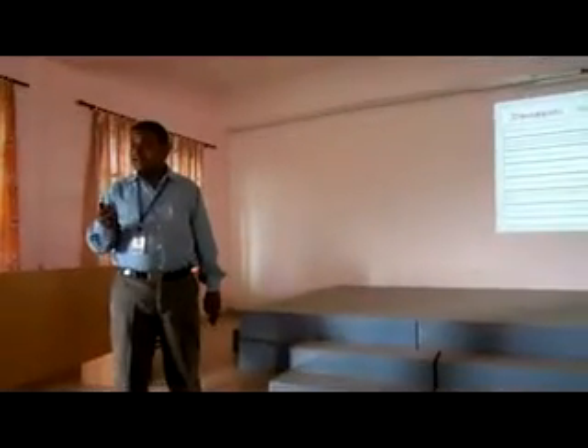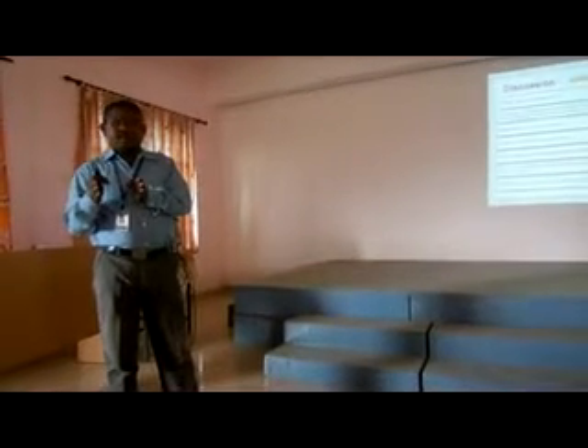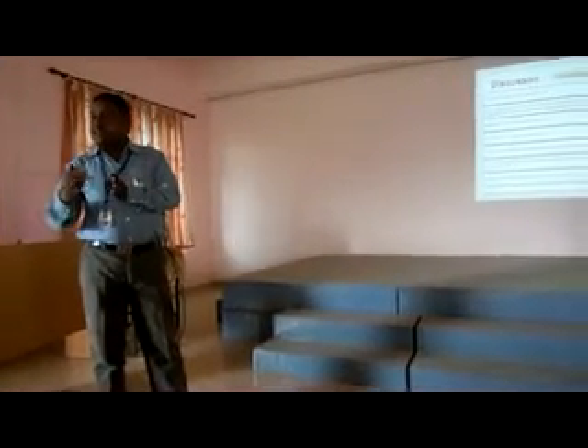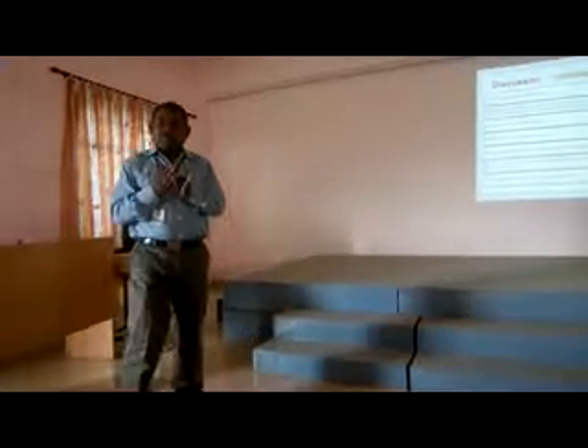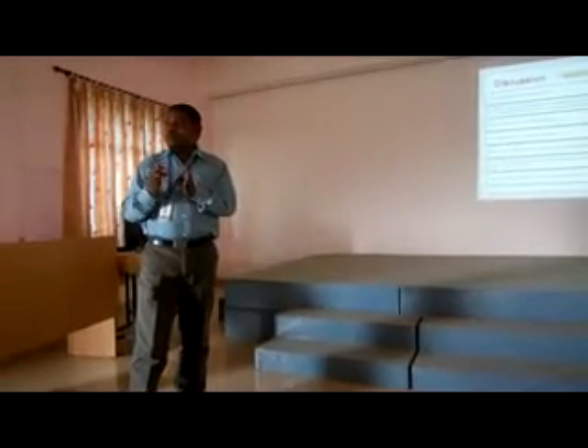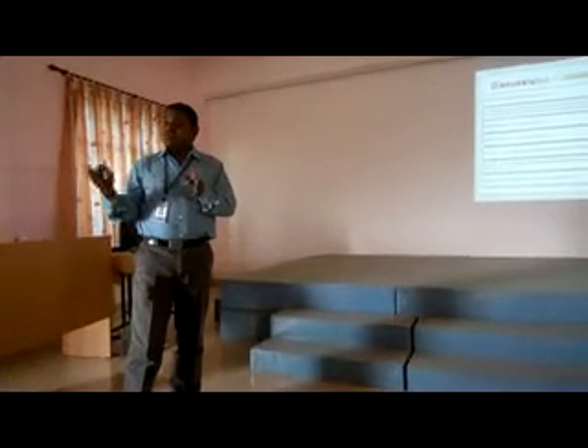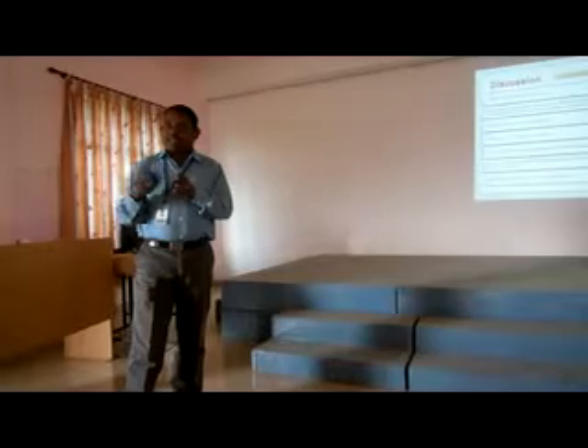So with respect to hardness, actually these kinds of base metals are quenched and tempered. When the material is quenched and tempered, it consists of martensitic microstructure. That is the reason these base metals offer very high strength in unwelded conditions. But that quenched and tempered martensitic structure is welded again. And in the heat affected zone, there is a possibility of again tempering the already tempered material. And also in the near weld zone, that is near your fusion zone, it takes a very long time for cooling. That is called a normalizing kind or annealing kind of treatment.